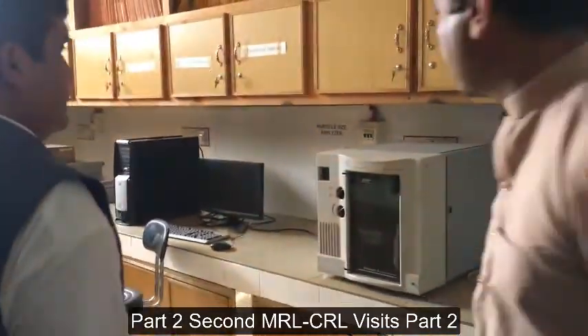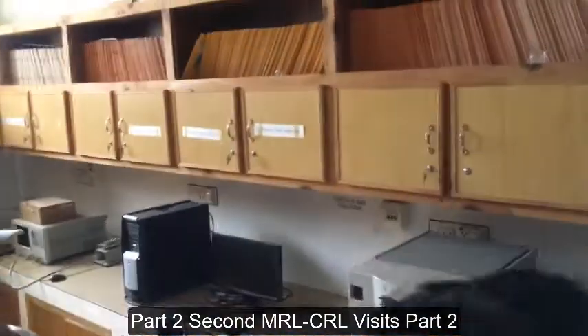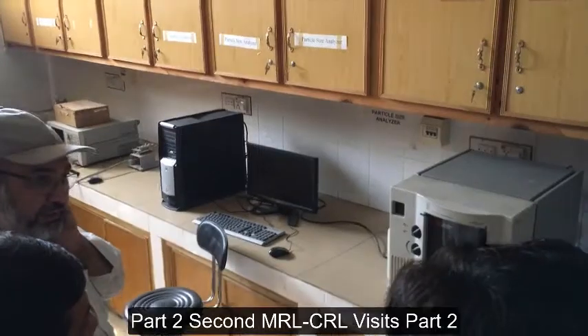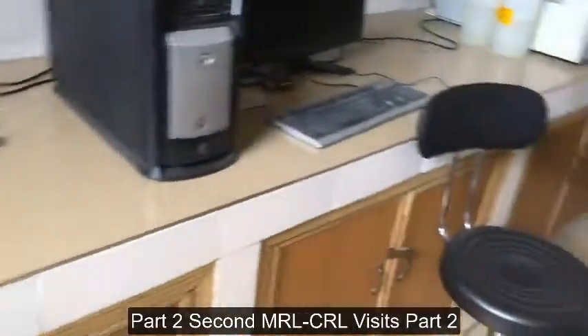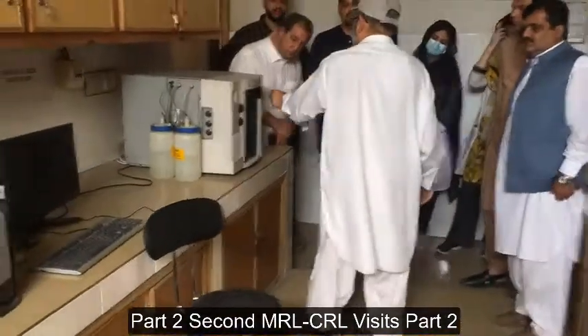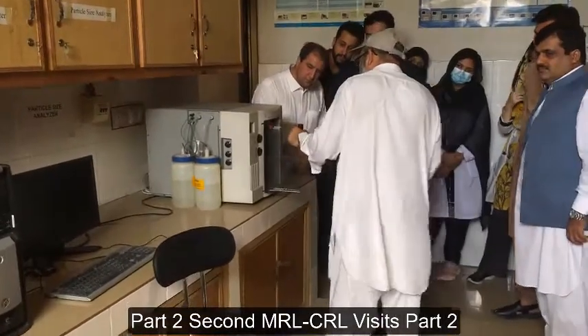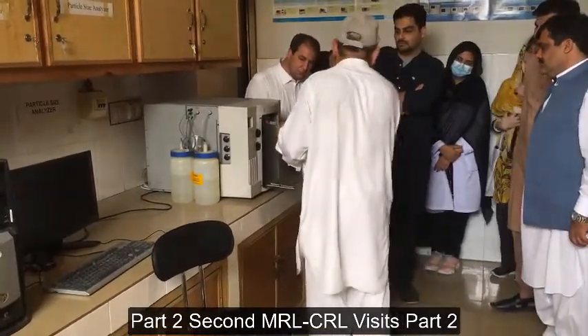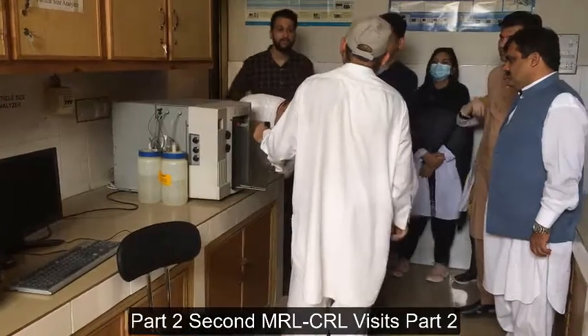Here we have a particle size analyzer, which I told you about. Sometimes we need a 5 micron particle size of the final powder after milling, sometimes we need 1 micrometer size, sometimes different sizes. So here we bring the powder sample and put it in that small beaker, and it tells us about it.